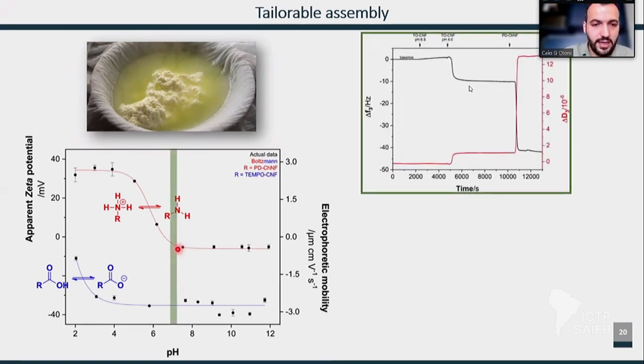So for instance, if we go for pH 7, there is a polycation, there is a polyanion, but the polycation is above the pKa. So it's not charged. You can see here from the electrophoretic mobility that the charge is almost zero. And the polyanion is above the pKa, so it's fine, it's deprotonated. Zeta potential roughly minus 35, minus 40, right? So neutral, negative, it will not complex. You can see here that nothing changes in the frequency. So we can mix them properly and then we can trigger the complexation.